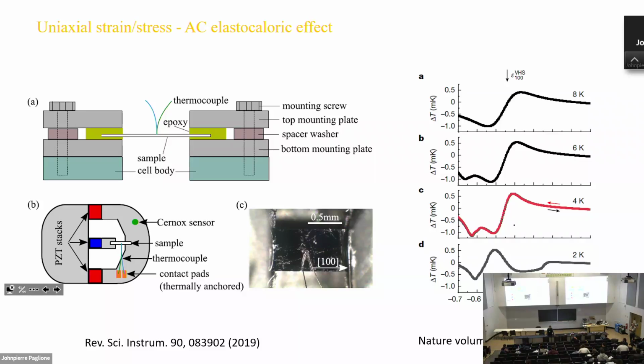Do you also perform magnetic measurement in the cell, or just... A magnetic measurement in which one? The piston cylinder cell. Once we got this coil, we tried to put that coil in the piston cylinder cell, and that can work. So, you said for the single cell, right? And also reduce the maximum pressure. How much pressure is that? Yeah, that one, because it's a single cell, you can only go to 1 GPa.